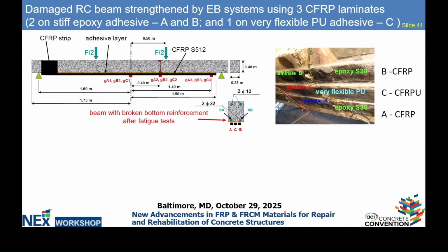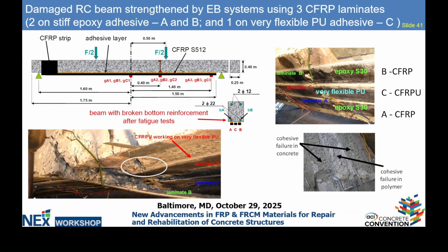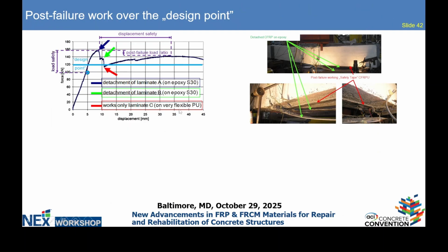So another case, we have a completely cracked concrete beam, 3 meters long. There are 3 composite materials, 2 with epoxy on both sides and 1 with a very flexible material in the middle. During the loading, both carbon fibers on epoxy detached and everything was hanging on this flexible polyurethane. So you can see when we assume the design point here and we go to the ultimate point, at these points the carbon fibers detach on the epoxy resin. From this point, everything started to hang. So we are still over the design point.